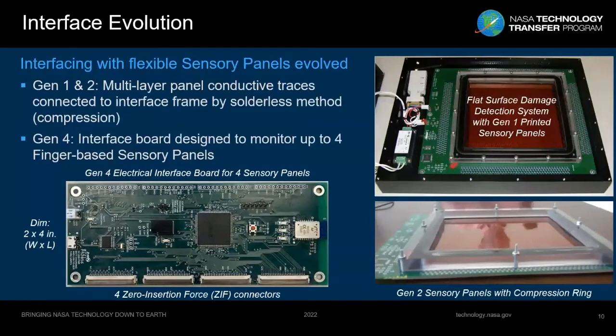So just as Tracy was talking about the sensory panel evolution, how we interface to these sensory panels also evolved. So you'll see there on the right, in that top right image, that's our Gen 1 and Gen 2 multi-layer panel. It's got numerous conductive traces. In fact, it's a total of 4 layers with 168 traces on each layer for a total of 672 traces. And so as you move down into the Gen 2 sensory panels with the compression ring, as Tracy had alluded to before, we developed this solderless method to interface all these 672 conductive pads to the interface panel. And we did that using a compression ring.